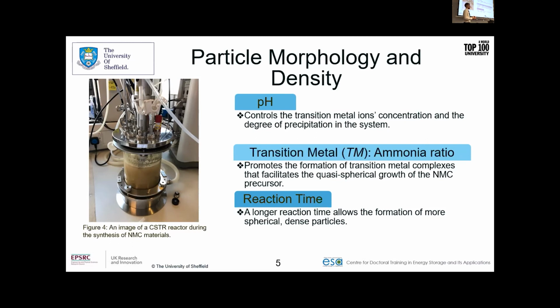So it precipitates too quickly, you form lots of small and irregular particles, and it doesn't really gel very well. It doesn't really form the nice desired particles that we want. It reduces the capacity, and they just don't perform very well.